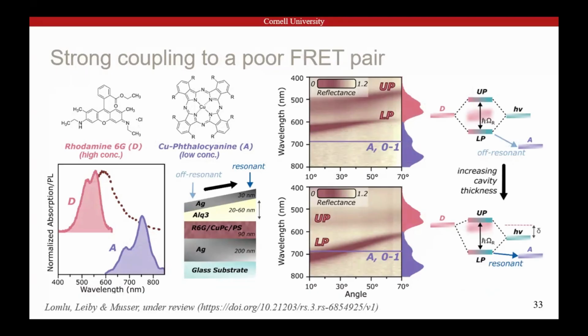And the nature of this system is then we can independently tune the concentrations of the species. So rhodamine is going to form polaritons. We can tune its concentration to change the Rabi splitting. The copper phthalocyanine acceptor, we can change its concentration to tune the donor-acceptor distance, which is going to cover the baseline energy transfer properties. And we can tune the length of our cavities with this wedge structure to sweep the polariton energy across the acceptor absorption band. So the first thing to check is, do these things transfer energy at all?